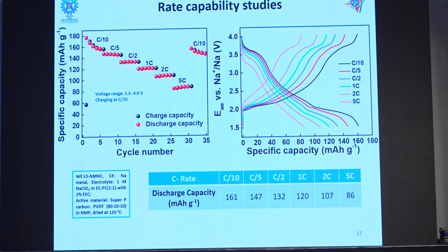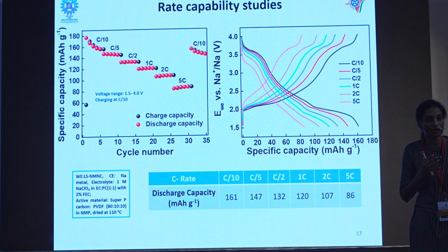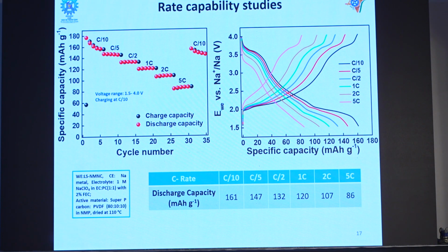And this improvement in the rate capability was found because we have a faster diffusion induced by the spinel component with a high electronic conductivity. So we have a very good rate capability, especially at 5C, we got 86 milliampere hours per gram, compared to half of that we obtained at C over 10. C over 10 means we are charging the battery in 10 hours and discharging the battery in 10 hours. 5C means we are charging the battery in about 12 minutes and discharging the battery in 12 minutes. So you see how fast we are charging.